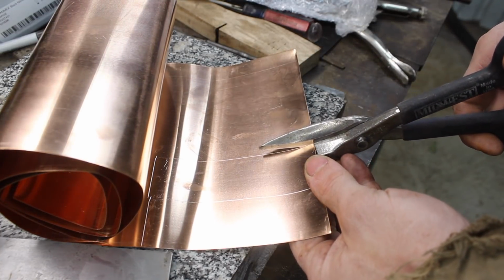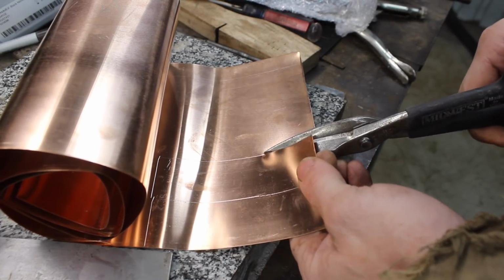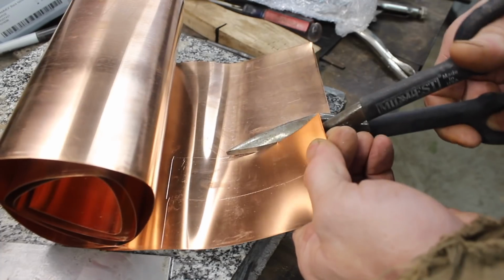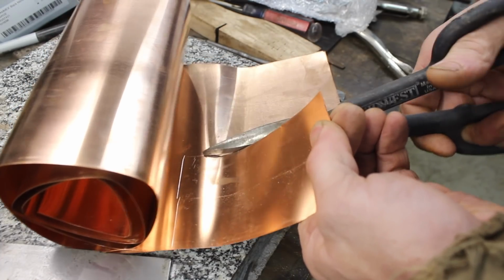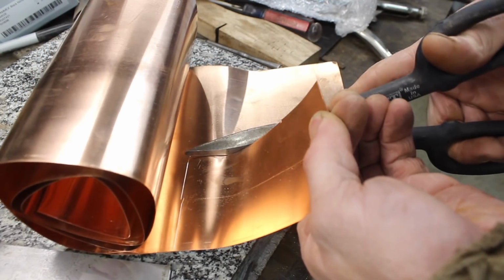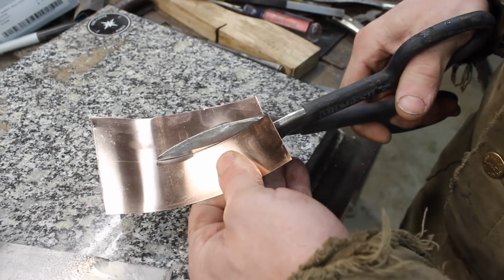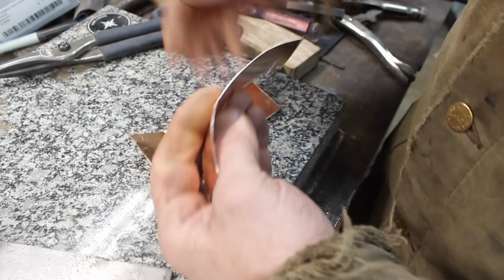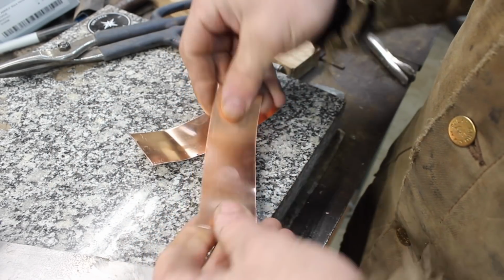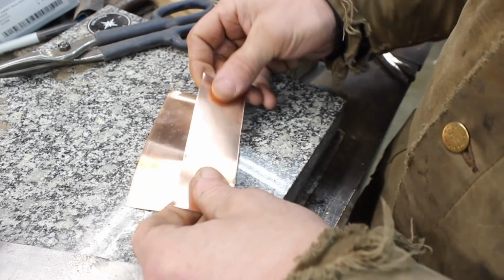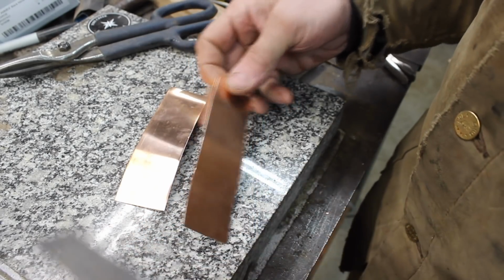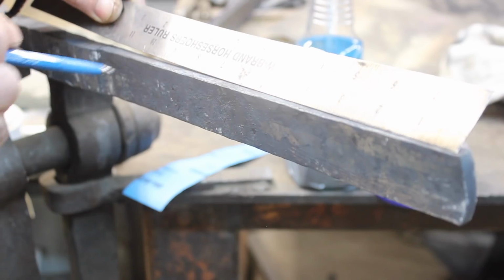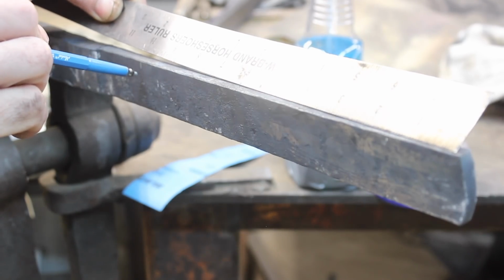I believe it's a 15 thousandths if I remember correctly, which should be plenty thick, because when you integrate something into a sanmai or laminate type blade and then you finish it out with the beveled grind, it reveals more than just the actual thickness of the material. And I don't want a super wide band of copper on this blade, just an appropriate amount.